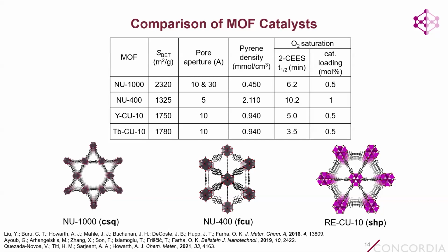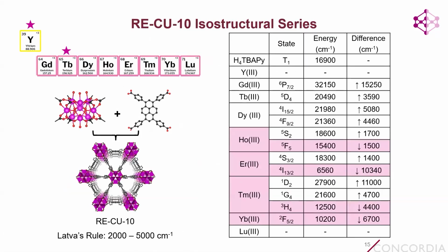But is this really the whole picture? Is it just pore aperture size and photosensitizer density in the MOF, or is there something more to it? And of course, we can't really look into that further if we only have 4 MOFs to look at. And so the next thing we wanted to do was test how the identity of the rare earth element in the metal organic framework would affect the generation of singlet oxygen and the subsequent photocatalytic results. And so initially, Victor made yttrium and terbium Cu10, and then he worked quite hard after this to make the lanthanoid analogs ranging from gadolinium to lutetium.